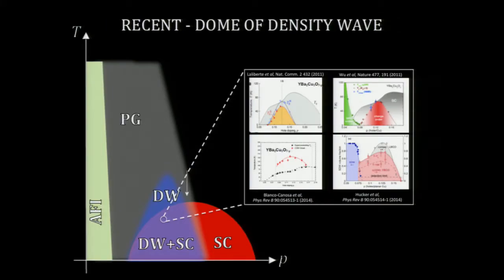Finally, in the last 5 to 10 years, scattering probes have found that, in fact, that broken symmetry state seems to constitute a dome in the phase diagram. So it seems to be something much more prevalent than maybe an oddity in the system.